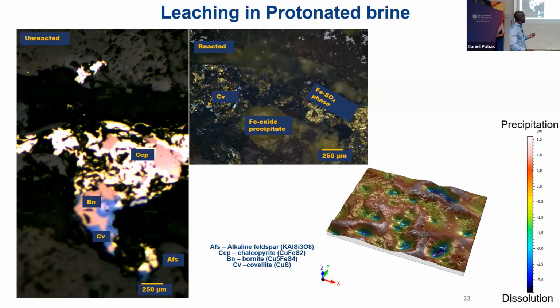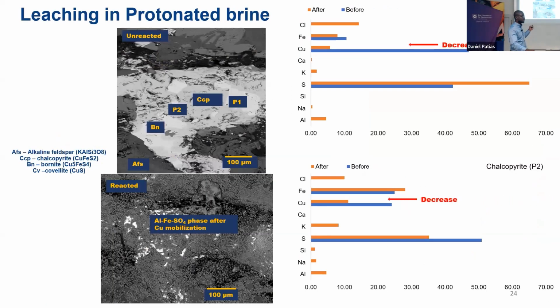So you have more ferric oxides forming. These are metastable, meaning they can form and easily go back again into solution. You have ferric sulfate phase forming as well. And then from the EPMA, we see that there is a decline in copper for both chalcopyrite and bornite, unlike the previous two cases which I've shown you.